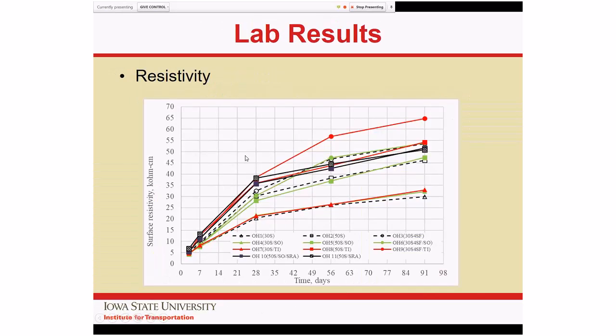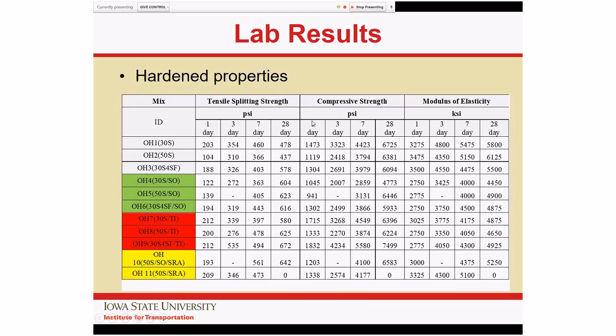One of the elements for the project was that for the internal curing deck we had a maximum slump of 5. There are several reasons for that. We actually wanted it to be lower, but did concede that there's not a lot of experience with pumping concrete at really low slumps in this area anymore. The reason for that really has to do with subsidence cracking over the top mat of the rebar. So there's a good purpose for that. During construction, that's probably the element that we heard the most complaints about from the contractor, the 5-inch slump max. But as far as pumping, it came through okay.